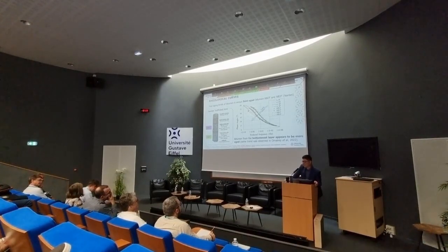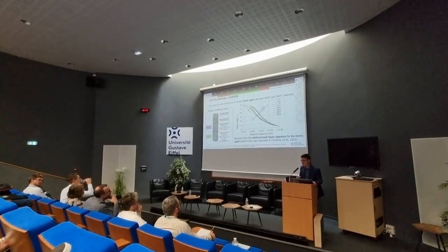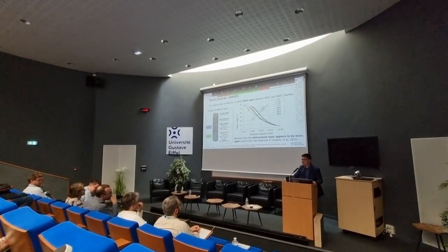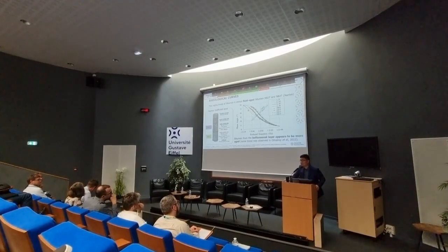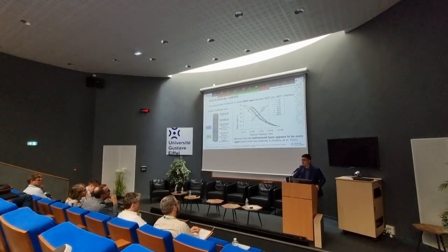It's very complicated because, for example, we also try to evaluate the possible impact that traffic could have on bitumen and also asphalt mix, which is why we always took asphalt mixtures from a traffic and a no-traffic road, because this would be the only parameter that changed between these two. But to be honest, we couldn't draw any sound conclusions on that because we couldn't see any clear trend. So I don't see. Okay.